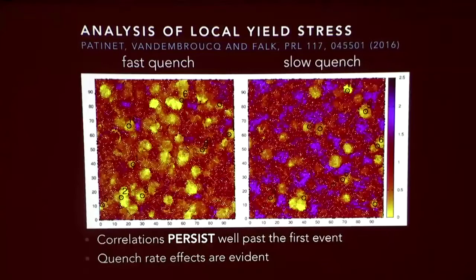We can also see distinct differences between materials that were quenched quickly and slowly. You can see many more local low yield stress regions in the quickly quenched glass, where the temperature is lowered very quickly from the liquid to the glass, than in the slow quench.